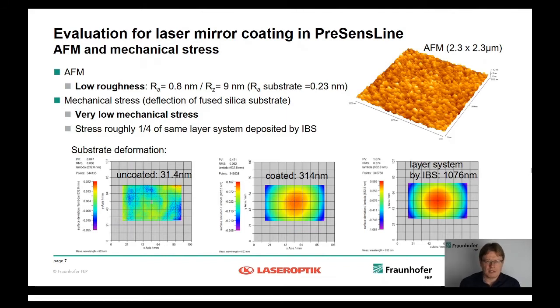Here's the AFM and mechanical stress measurement. We achieved a low roughness below 1 nanometer and a very low mechanical stress. This was actually considerably lower than that of a reference system that was deposited by IBS. IBS is ion beam sputtering. The ion beam sputtering was done by Laser-Optik. And the stress was only a quarter of this, and this is good for many applications, also for the laser mirror coating. Usually this leads to a better stability of the layer system.